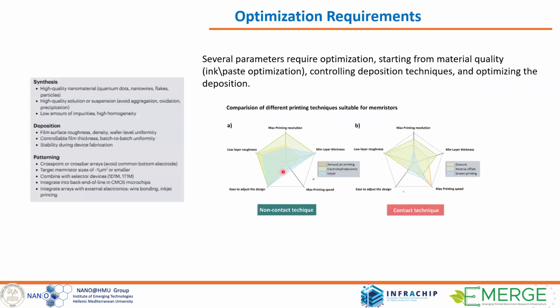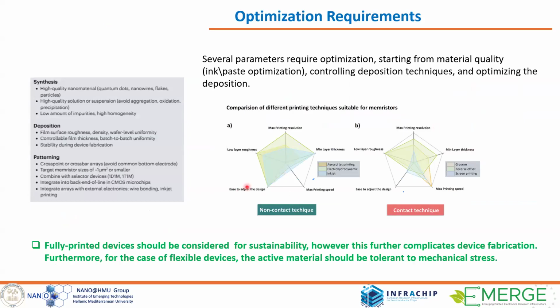Okay, some details about the printing technologies. The message here is that a fully printed device should be considered for sustainability. Here, the electrode type is important. We have to avoid noble metals if we can. This is the main limitation, that we are still using silver or gold for our contacts, but there are alternatives like graphene or carbon-based paste with quite good conductivity. And of course, we can recycle these electrodes and they are much cheaper compared to noble metals.